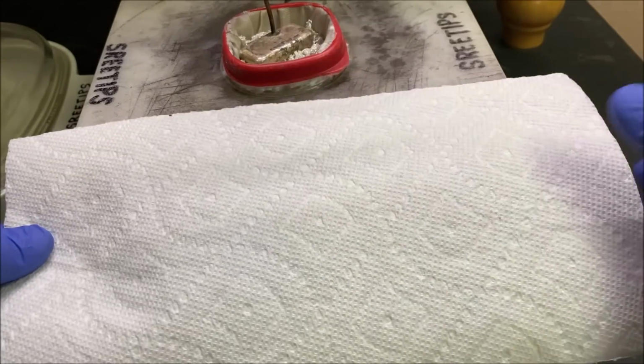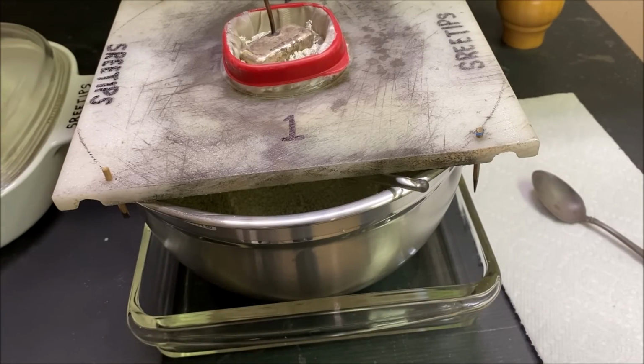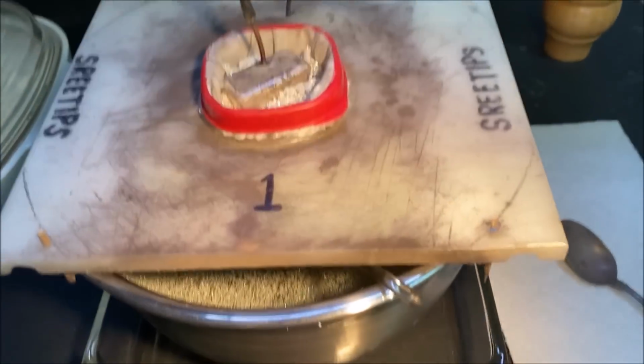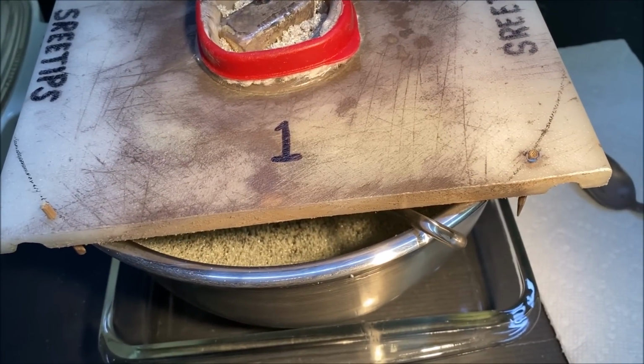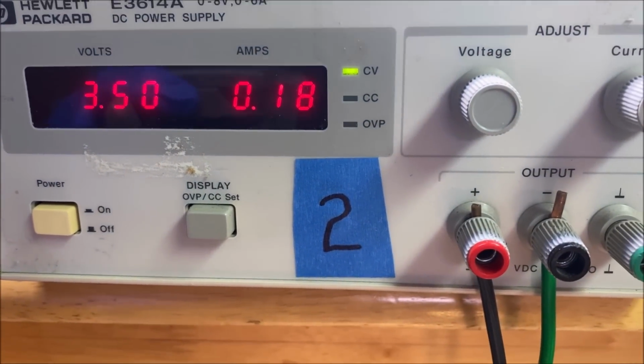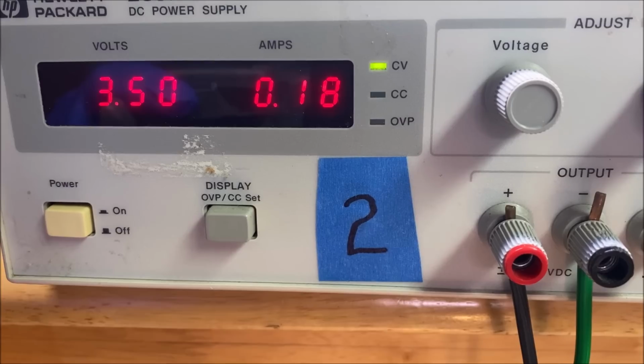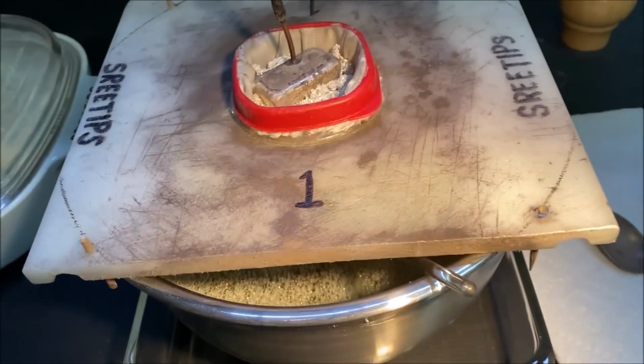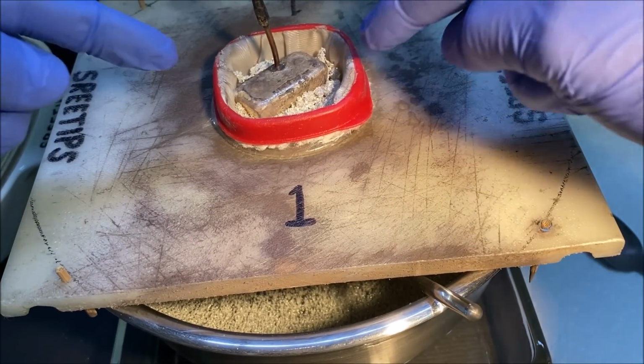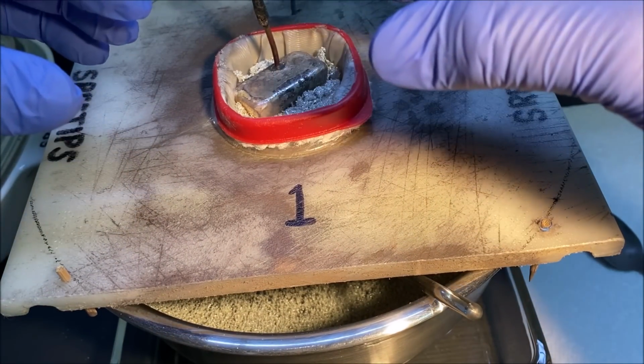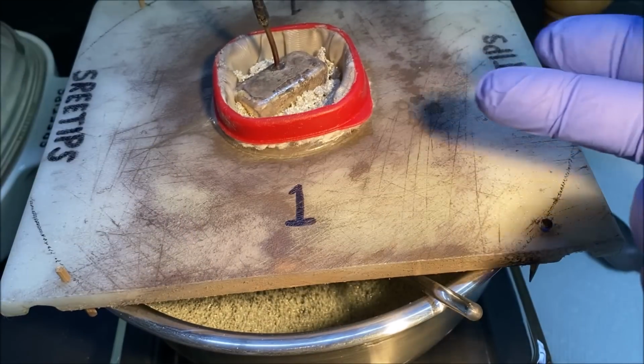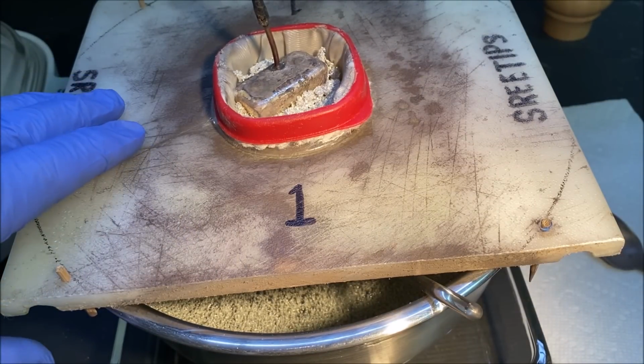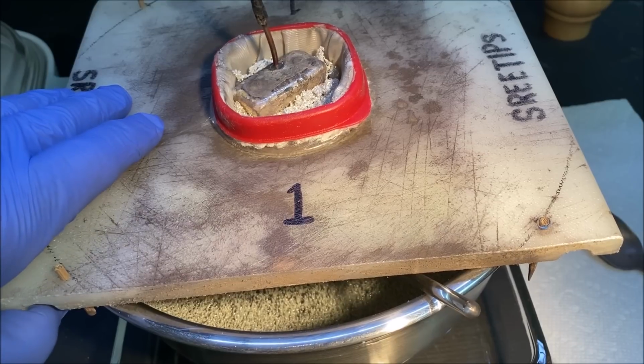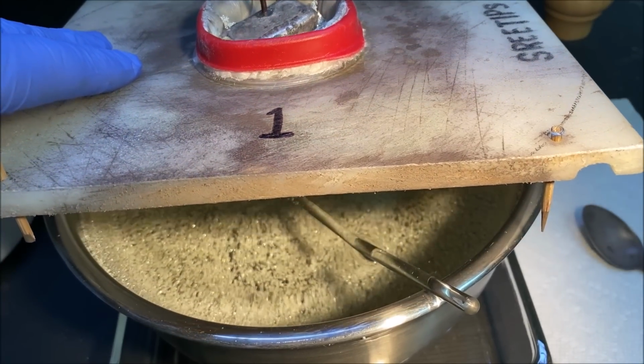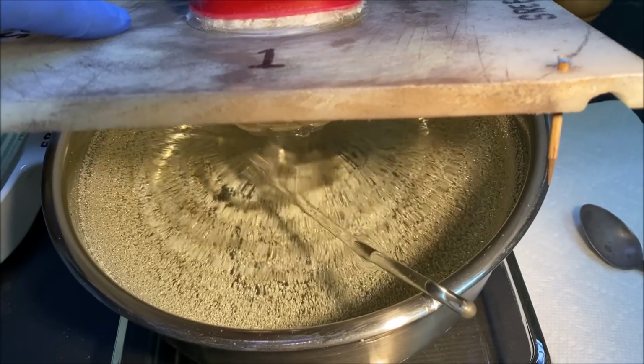About 18 hours into the experiment, and if you look down in here, you'll see the pure silver crystals forming up nicely down here. Let me show you the amps first before we get too far ahead. Amps have dropped way off, less than 1 amp. And I think what's happening, like I spoke in the previous segment, the crystal in here is forming a bridge. The bottom's getting dissolved away, and then it loses contact with the electrolyte in here. When I pick this up, it'll probably reestablish that contact as the silver moves down in the basket.